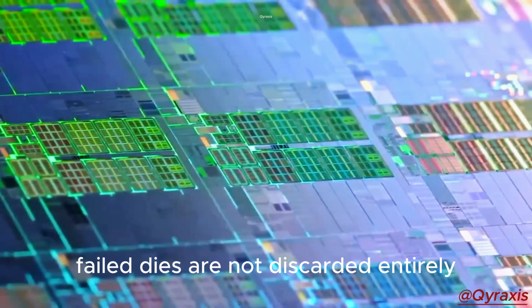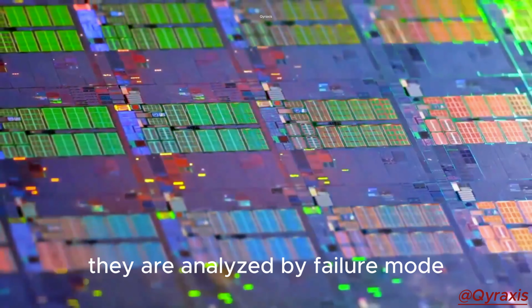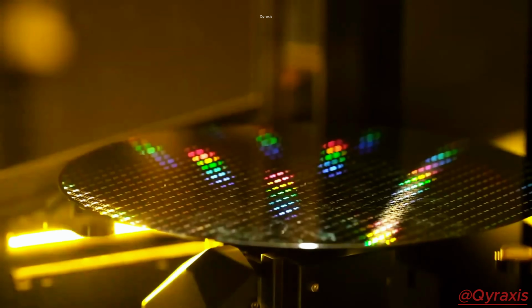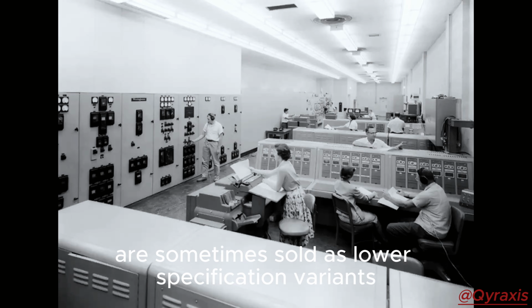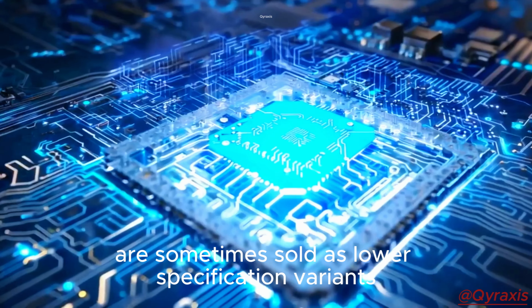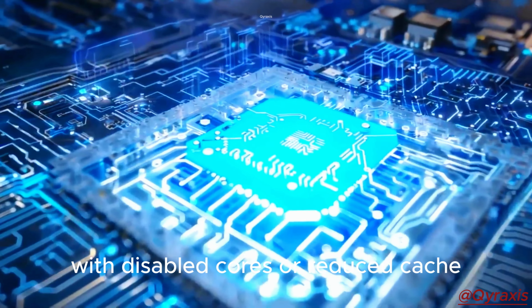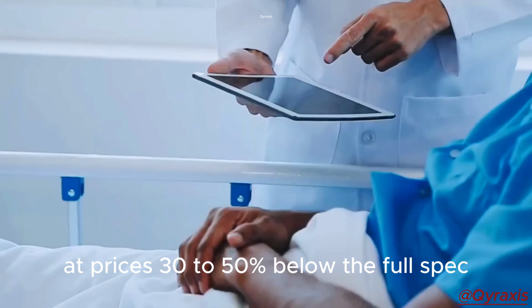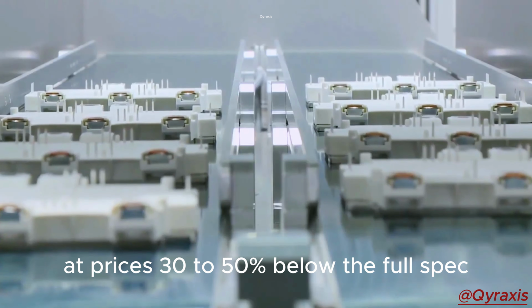Failed dies are not discarded entirely. They are analyzed by failure mode. Those with only minor defects are sometimes sold as lower specification variants with disabled cores or reduced cache, at prices 30 to 50% below the full spec part.